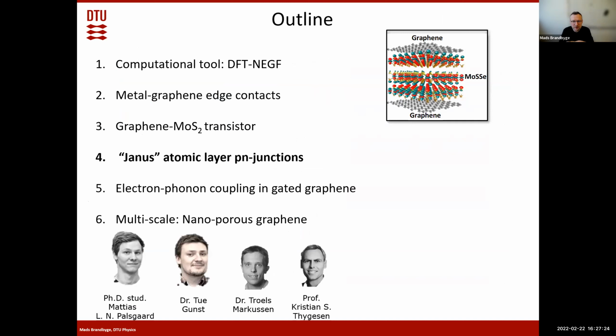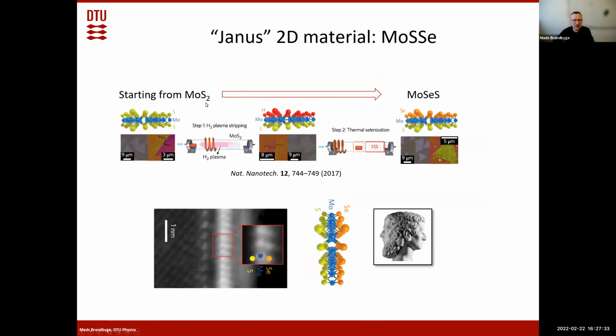Let me move on to some materials which are less standard, and these are called Janus materials. The basic idea is that if you take something like MoS2 and put it on a surface, you can strip the sulfur in a process, replace it with hydrogen, and then in another process step, you can replace the hydrogen by selenium. Then you have made a dichalcogenide 2D material, but it's a Janus material in the sense that one face is different from the other face. This illustrates in this two-dimensional material business that you have standard materials, but you can not only stack these in new ways, you can also take the material and even change the two faces of the material. So there's a huge number of possibilities.